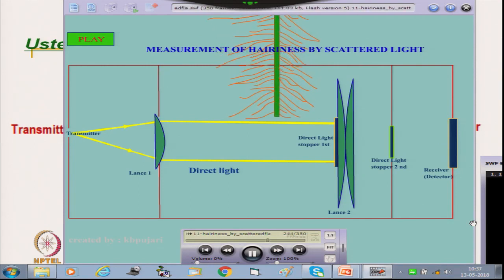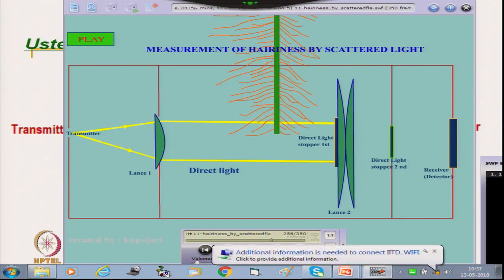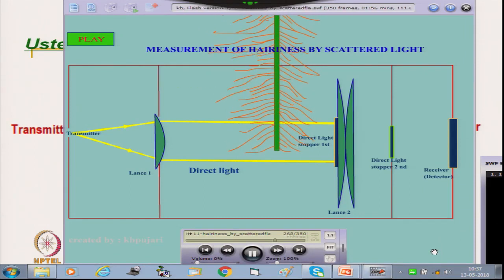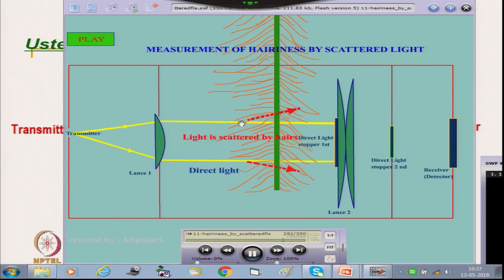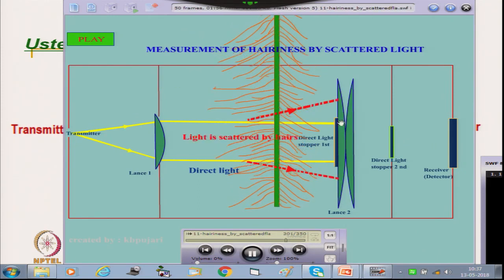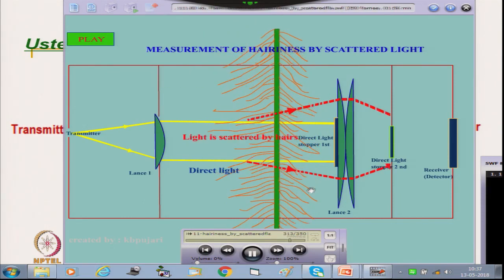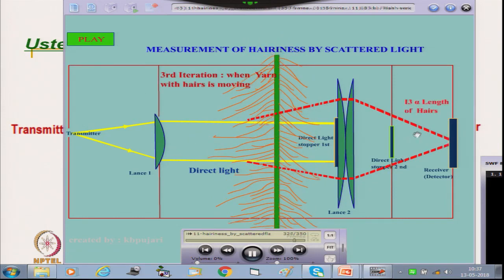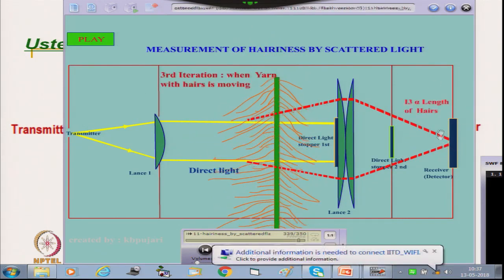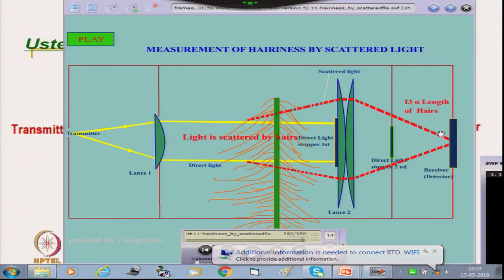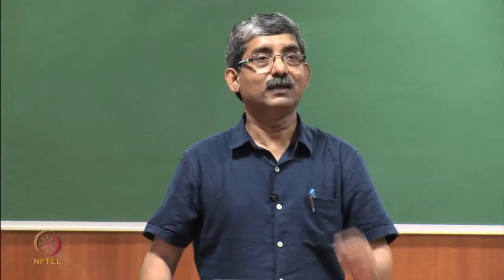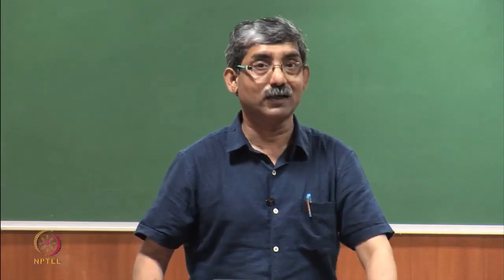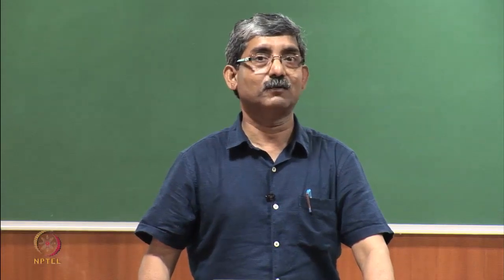Now let us see yarn with a large number of hairs. The hairs start scattering the light beyond the stop mechanism, and through the lens system it gets projected. The amount of light received is proportional to the length of the hair, so indirectly by measuring this intensity we can get an idea about the total length of the hairs.